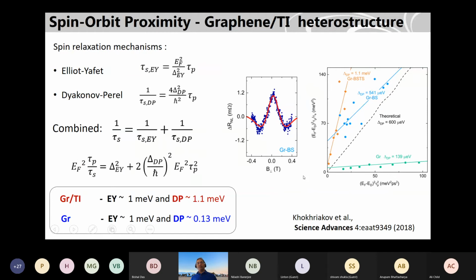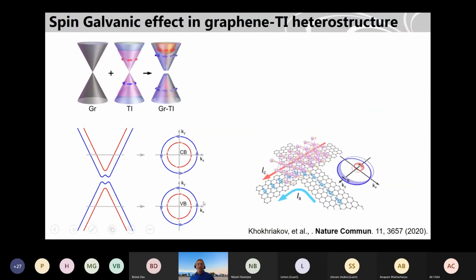But when we calculate the spin-orbit coupling strength, as I showed you in the previous part of the lecture, we combine the Elliott-Yafet and D'yakonov-Perel mechanisms, use this formula, and find the spin lifetime for different gate voltages and plot it here. This is from the Hanle measurements. This is for only graphene, and this is for the heterostructures. We again find this D'yakonov-Perel mechanism, which is due to broken inversion symmetry in the system, and it is a bit higher here. So that was quite helpful.